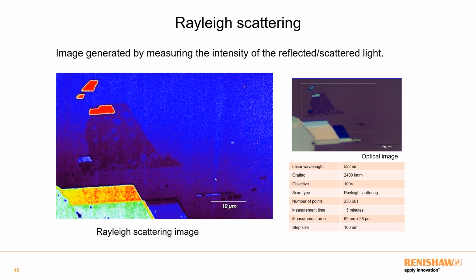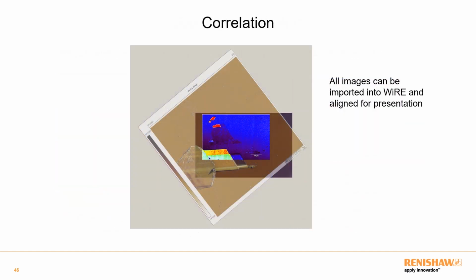The other thing to note is our rhenium disulfide layers. In the regions where we know we've got thin layers, it tends to be darker than the substrate. But as we go to regions with more and more layers, so I think we've got 4 and 5 down here, you can see that it becomes lighter than the substrate. And when we go to very thick material, it scatters much more than the substrate. So this is interesting, and this highlights the need for a bit more thought and a bit more study here. And we'll show that in a minute.